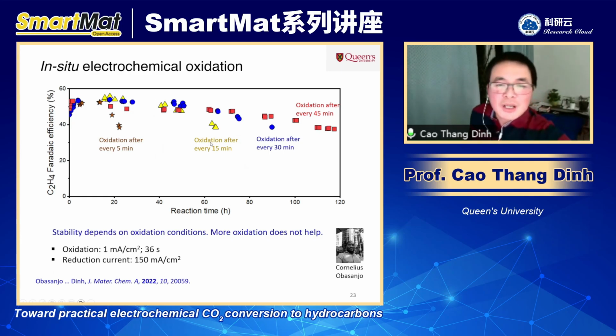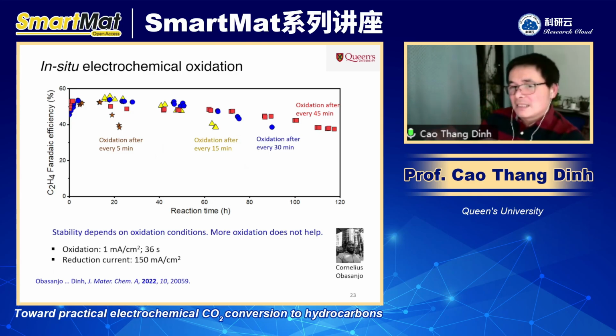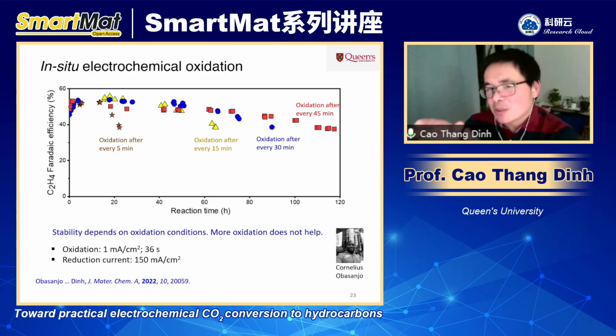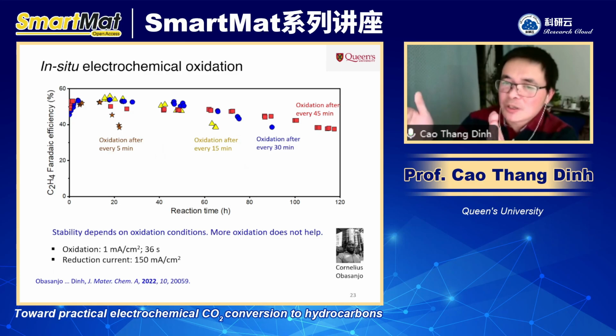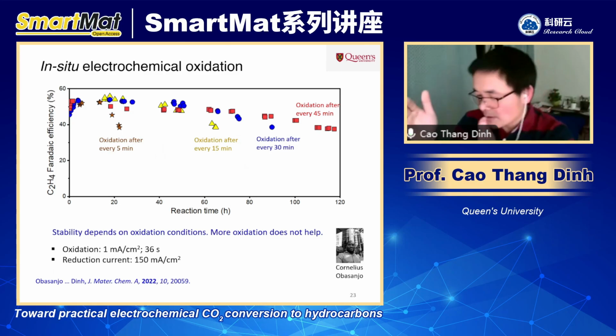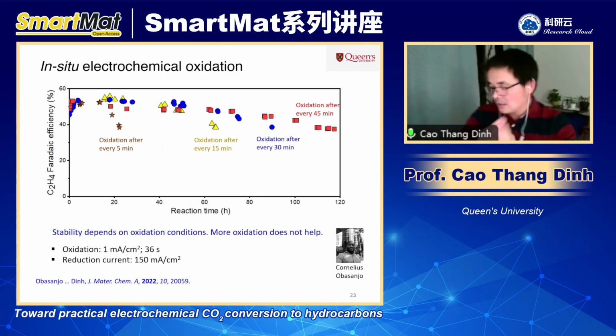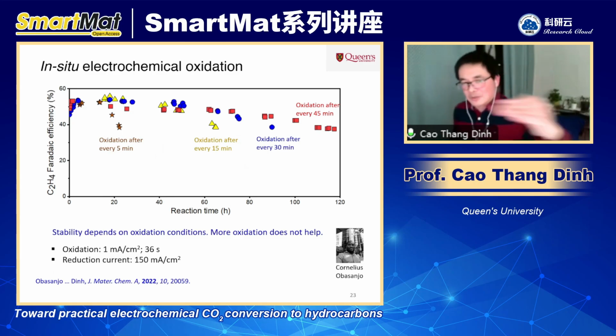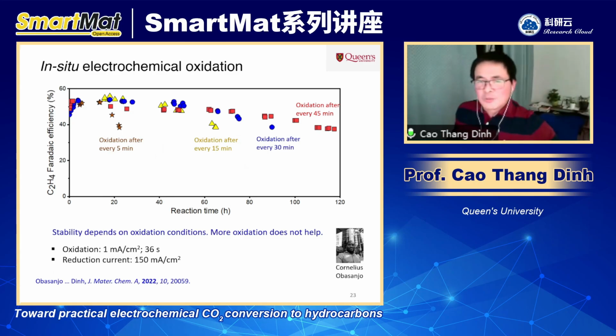Right? Now, if you oxidize every 15 minutes, well, the system is still in the same oxidation condition, at least the oxidation condition here. But the point here is that by controlling the oxidation and reduction time, you can extend the lifetime of your catalyst. Right? So it seems like the approach works, right? So you extend the lifetime to more than 100 hours.